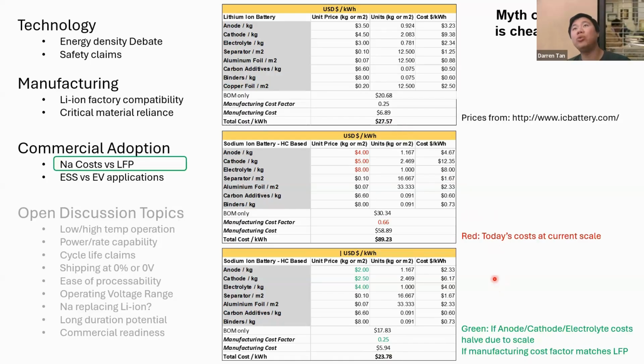So I'd say to a lot who are skeptical, I agree if these numbers are never reached, but a lot of people also believe that the LFP numbers wouldn't have been reached 10 years ago. 10 years ago, LFP was lower energy density than NMC, was lower scale, higher cost, and it took time to get there. So I cannot predict when this will occur. It could be 5 years, 10 years, 20 years. Not even sure in our lifetime, but if it were ever to occur, these will be the conditions that need to be met.